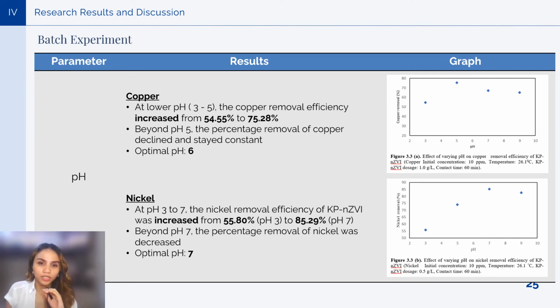At lower pH, the removal efficiency of copper increases from 54.55 to 75.28%. For nickel, at pH 3 to 7, the nickel removal efficiency of the KPNCVI was increased from 55.8 to 85.29%. Beyond the optimal pH for both heavy metals, the percentage removal of copper and nickel declined and stayed constant. The optimal pH for copper is 6, while the optimal pH for nickel is 7.